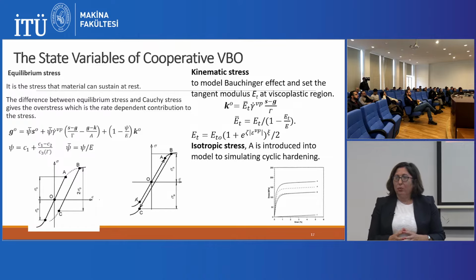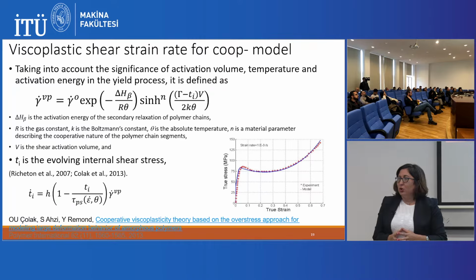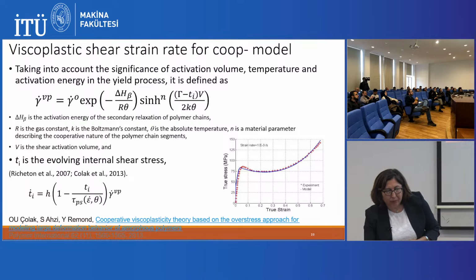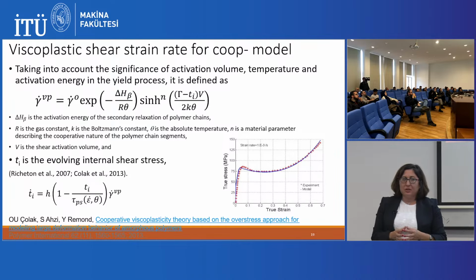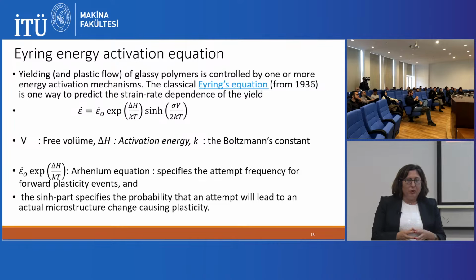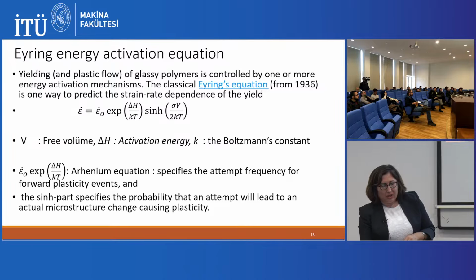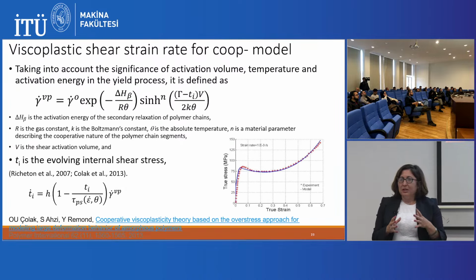Another important formulation is the viscoplastic strain rate. This viscoplastic strain rate, considering the Eyring equation, is this one. In 1936, Eyring defined this formulation, and he considered that yielding is controlled by some energy activation mechanisms, considering the activation energy and free volume, etc. Considering this formulation, I implemented or modified it and used it in the VBO model, considering this Eyring formulation.